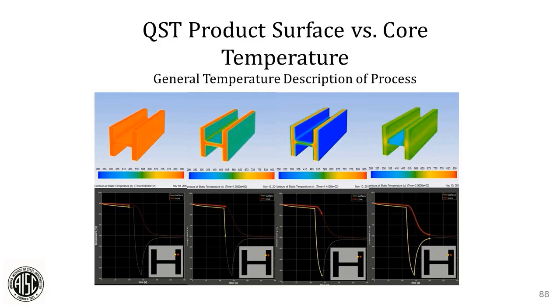And this is another quick look at what's happening during the quench and self-tempering process. The bar at the very first point, where it's orange, has not been quenched yet. Now you'll see the temperature drop, the yellow line in the second little graph representing the outside of the piece, the red line representing the inside of the piece. The cooling effect hasn't affected the inside temperature yet, but when you look at the third graph, you'll see that the inside temperature, the red line, is starting to be drawn down. By the fourth graph, you'll see where the self-tempering is actually happening. The surface temperature is going up and the core temperature, the red line, is going down, and that's the point where we need to hit that surface of 1100 to 1300. Next slide, please.